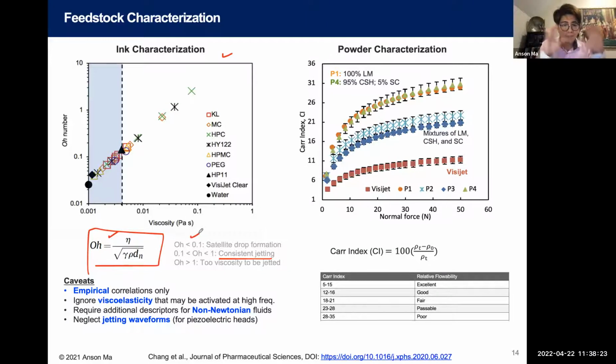But today, I don't think we have a lot of time to cover that. But conversely, if the viscosity is too high, it's also problematic because you don't have enough energy to jet the material. If you look at a lot of literature in inkjet, this is usually a good starting point. Let's say you create an ink, you measure the viscosity, the surface tension, the density, you know the nozzle diameter, then you can calculate this number, and it gives you a sense how far off you are from this magic regime of 0.1 to 1.